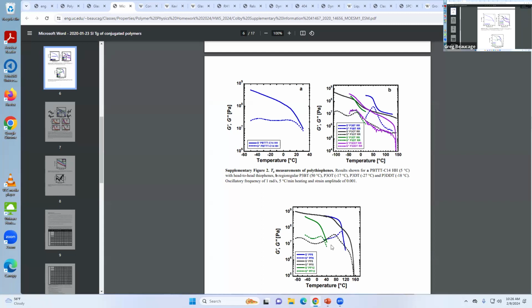So if you want to shift it to the left, right? So you want to add longer and longer side groups. So you want to shift that further and further to the left so that you can get it to be a liquid above the glass transition at room temperature, and that's useful for flexible electronics. I mean, he doesn't mention that when you put longer and longer side groups on it, it doesn't conduct anymore. So it's no use, but that's a feature he didn't mention. Didn't come out in a review of this thing, right? But so basically, the crux of this thing is add longer side groups so you can shift this around.